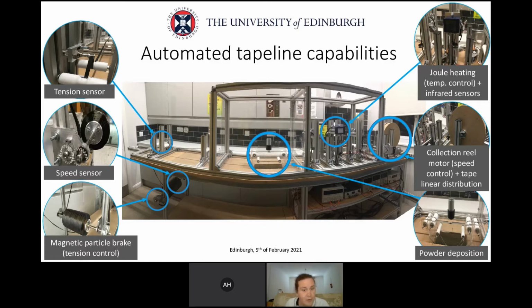We then have the powder deposition box in which the fibers are being coated with positively charged powder particles in a dust, a cloud or mist. We then have a Joule heating system to melt the powder, which is extremely efficient and requires very little powder. It uses the self-heating Joule effect, the intrinsic capabilities of the carbon fiber epoxies. And then we also have a collection reel at the end with a linear tape distribution to make sure that the tape is well distributed.